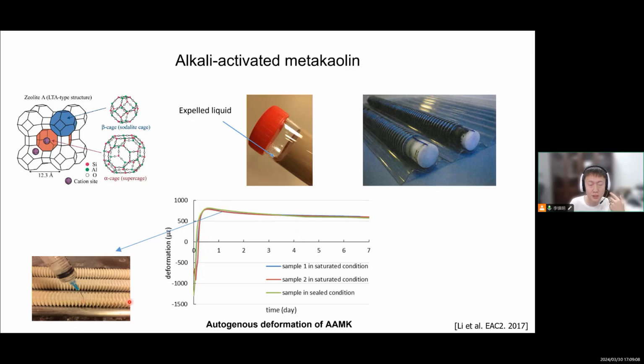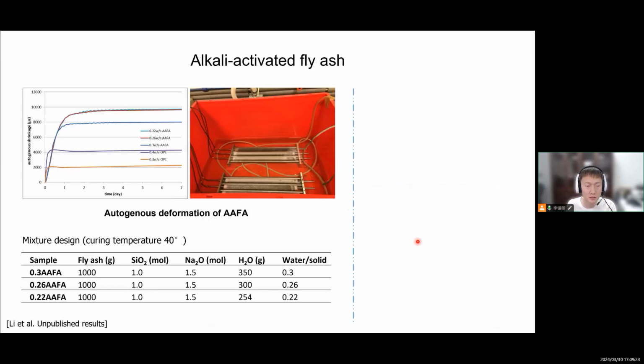I provided enough solution to surround everywhere so that it was in a totally saturated condition. But we can see the shrinkage happens again. So that means self-desiccation is not actually the mechanism behind the shrinkage. The same applies for the alkali-activated fly ash system.